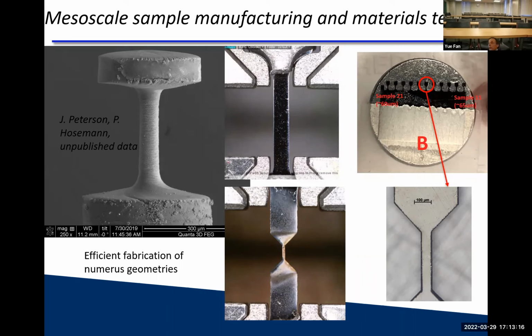So, but yeah, and then of course you can do heat treated, right? And then you get it crystalline and do the other way. We did it also the other way around in silicon. So in silicon, we did single crystal silicon and then helium implanted that. And first you see amorphization, but then you see more and more helium bubbles building up subsequently, right? And ultimately you get a cleavage at some point, right? So in that instance, unfortunately, you can't do the one-on-one comparison because you always get amorphization. So you can't do helium without the amorphization. But that was also quite fascinating